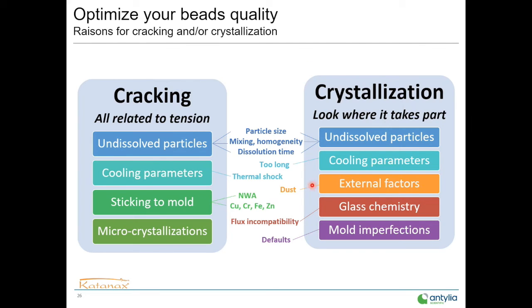Crystallization, we have external factors. Some fluxes will not be very well protected against the environment, and a cool airflow or a little dust landing on the beads during cooling can lead to crystallization. Glass chemistry, we looked at this a little bit when we talked about the flux earlier. If you don't have a good match between your flux and sample, you can create crystallization by the wrong glass chemistry of the mixture of both. Mold imperfection. The mold surface is very important to keep clean for XRF reasons, but also because defects in your mold can be a starting point to align the molecules in the fusion mixture and start crystallization.